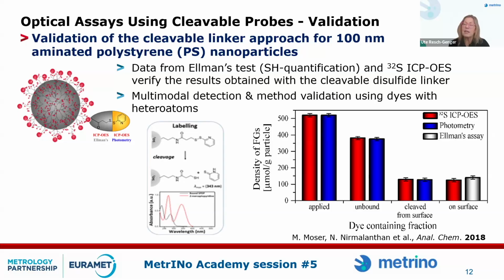And when you take a look at method validation, you see how much amount was applied, then how much was cleaved off from the surface, and what you find on the surface with different methods. So photometrically, and with ICP-OES. And thereby, if this fits within the respective uncertainties, you have your method straightforwardly validated.